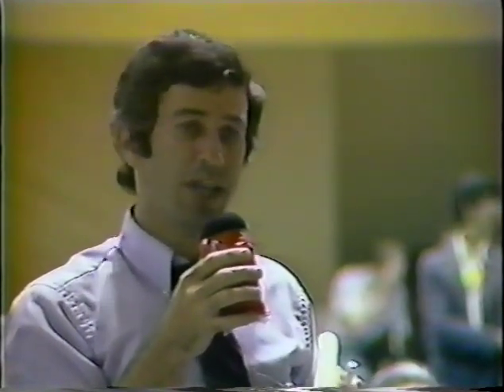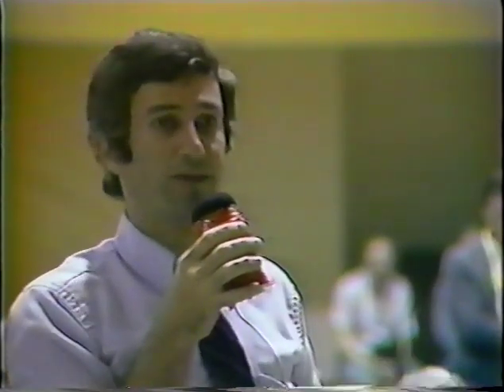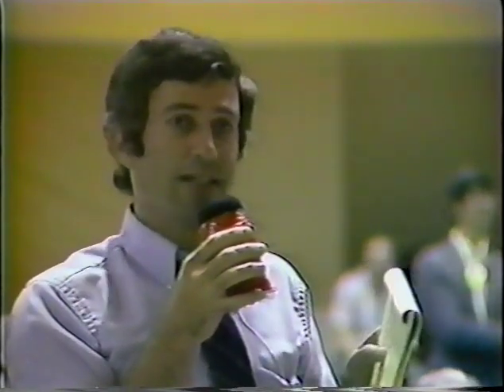Nate Lewis, Caltech. I have a comment and a question for Dr. Storms. The comment is that it's well known to people who try to make palladium reference electrodes that you often need to anodize surfaces in order to remove catalytic impurities. The palladium will dissolve. For people that are interested in this, there's a book for people that don't know much about electrochemistry. It's called Experimental Electrochemistry for Chemists, and it's by Sawyer and Roberts. And it describes all of the activation procedures necessary to allow palladium to sorb deuterium on charging, hydrogen actually, for reference electrodes. So I think it's a common phenomenon that some activated samples have to be anodized first to make them sorb deuterium.